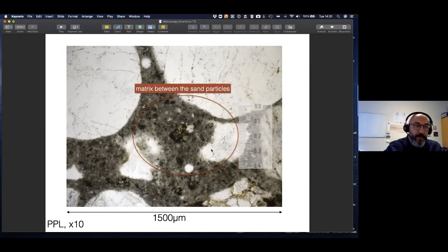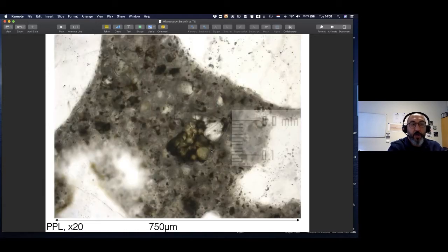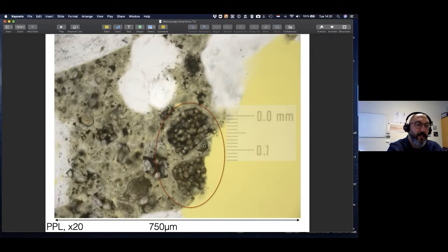So one example here, if you're interested in finding out if you have ordinary Portland cement, of course, what you need to look for is a lot of unhydrated cement grains full of belite and alite. And here is one example, perhaps you can find the spot between your aggregate particles. That means your binder. You can zoom in gradually to observe all these alite grains and belite clusters typically. This is, again, just one example.